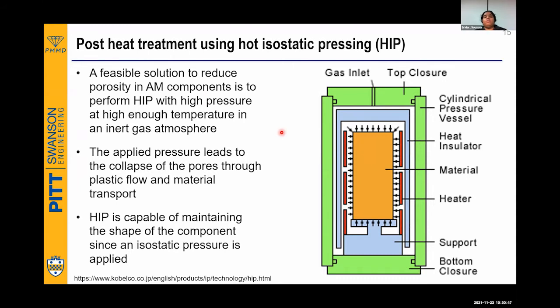So what we want now is pore closure, either collapse of pores or pore closure. The pore closure or the collapse of the pores is going to happen through either plastic flow or through some material transport. But why HIP? As I mentioned earlier, and as I emphasize, additive manufacturing is a near net shape forming process. So I should not do any post heat treatment process that is going to spoil the shape.